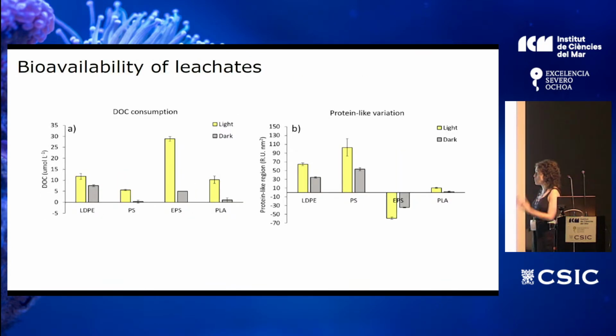And regarding the viability of these leachates, of these plastic types, we found that the highest consumption of DOC took place in the EPS treatment, in the irradiated one, and the others present similar results, including also the biodegradable PLA. So I would have expected also that the chemicals released, the organic matter released by the PLA would be more bioavailable to microbial uptake because it was a biodegradable plastic, but it wasn't.